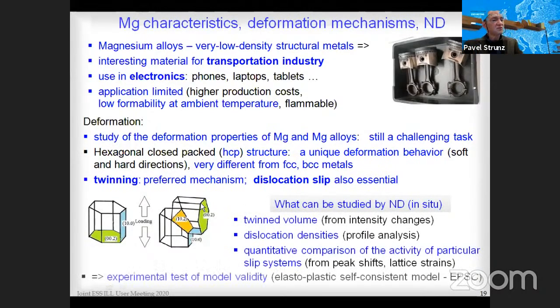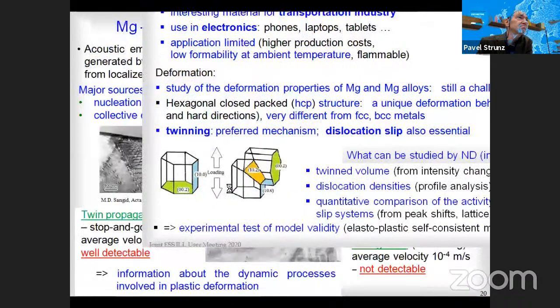By neutron diffraction, we can study twinned volume, we can study dislocation densities, or we can also do quantitative comparison of the activity of particular slip systems. All these things are important for experimental testing of deformation model validity.